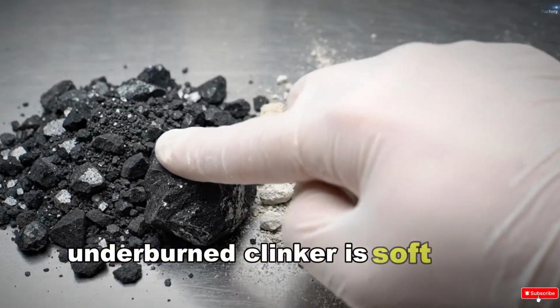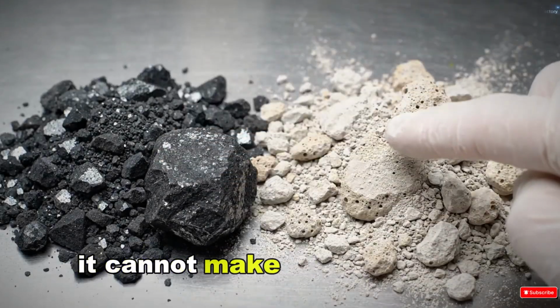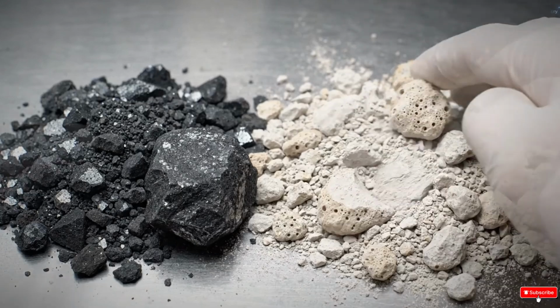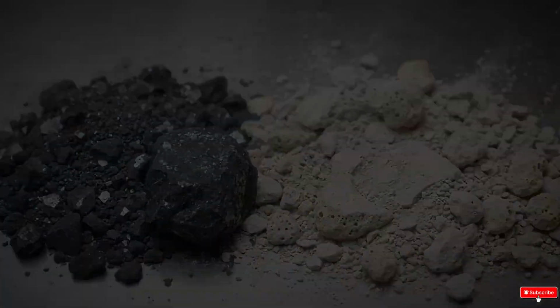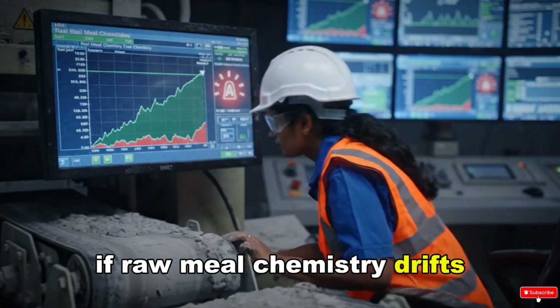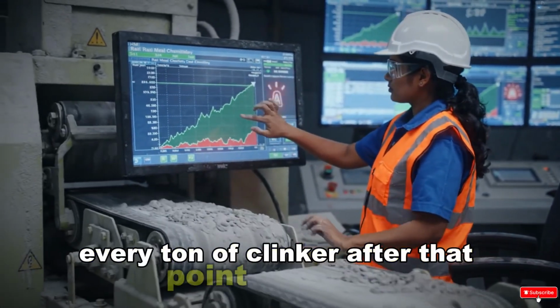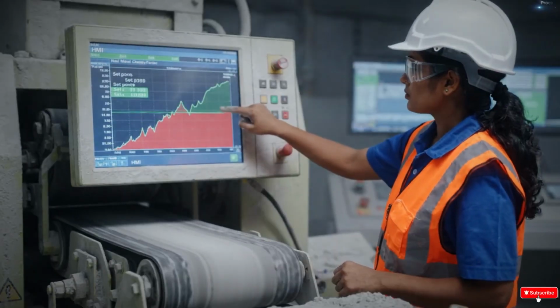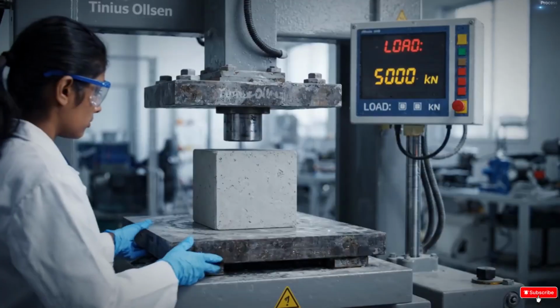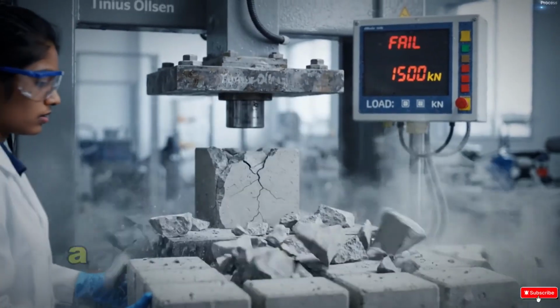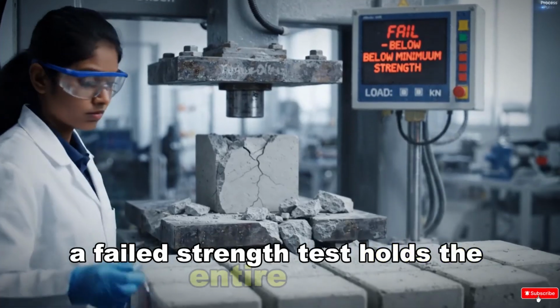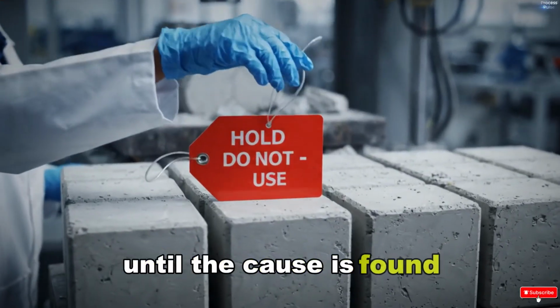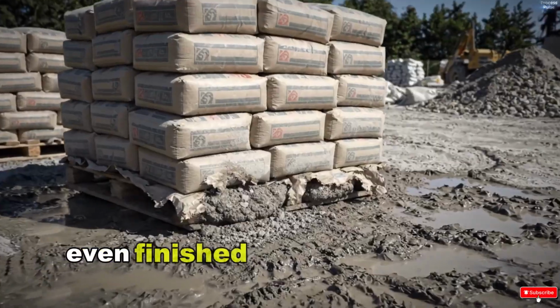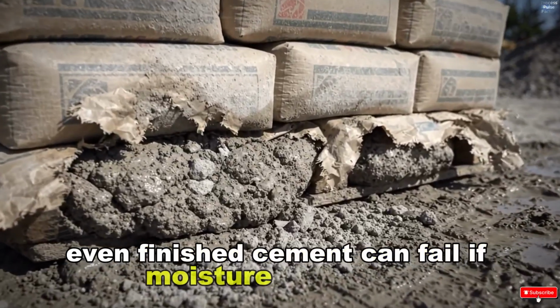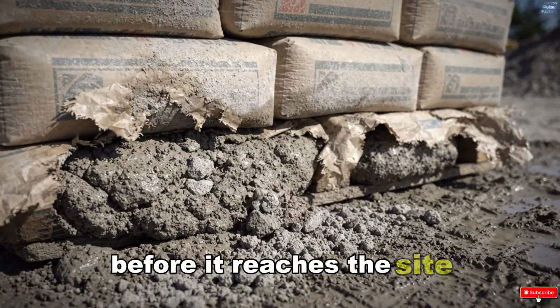Underburned clinker is soft and pale. It cannot make proper cement. If raw meal chemistry drifts, every ton of clinker after that point is off-spec. A failed strength test holds the entire batch until the cause is found. Even finished cement can fail if moisture reaches it before it reaches the site.